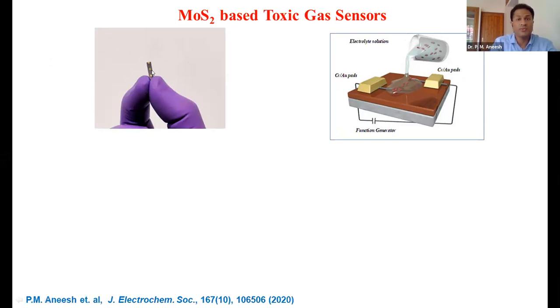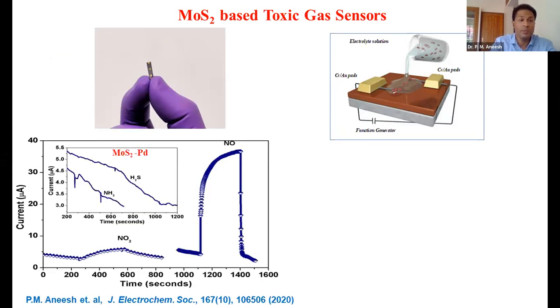And after that, we checked the gas sensing property by taking the current from the devices. So this is one of the devices we fabricated, a palladium topped MoS2 sample, and it's showing no effect to H2S and NH3, very little effect to NO2, but at the same time showing very good response to NO gas. So you can clearly see that the sensor can detect NO gas in a good manner. So that tells you the selectivity of your sensor.